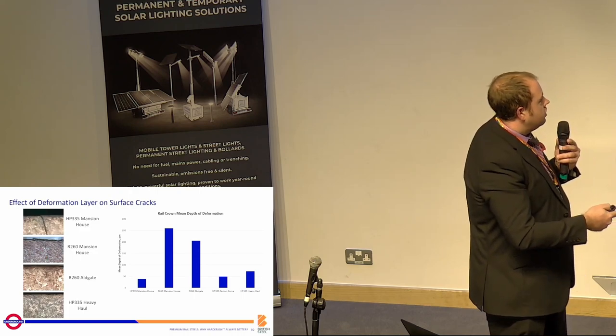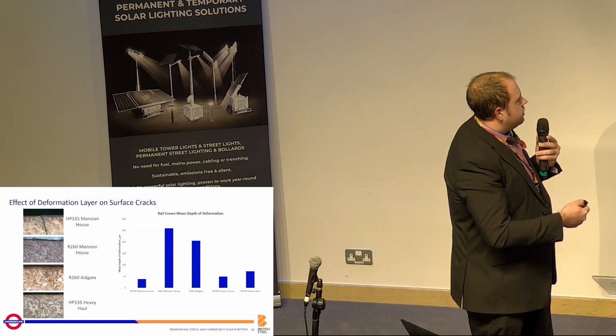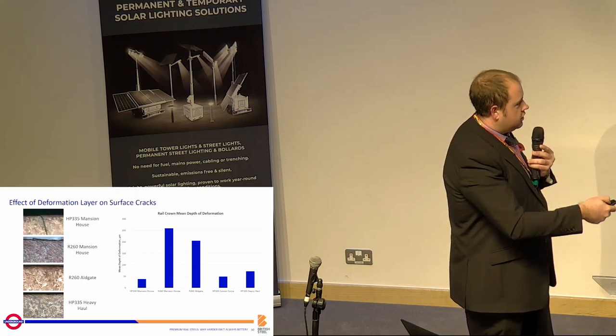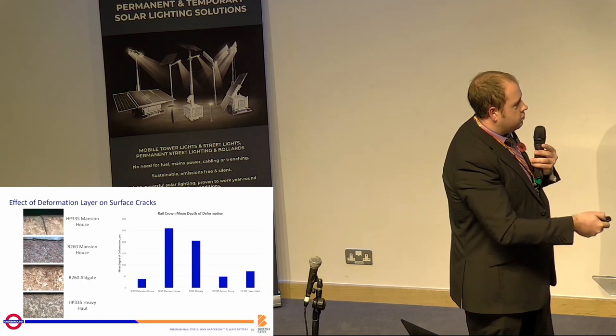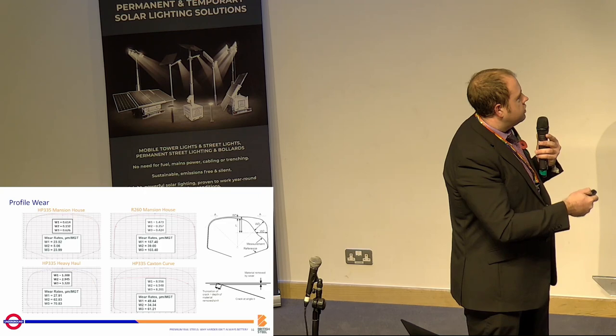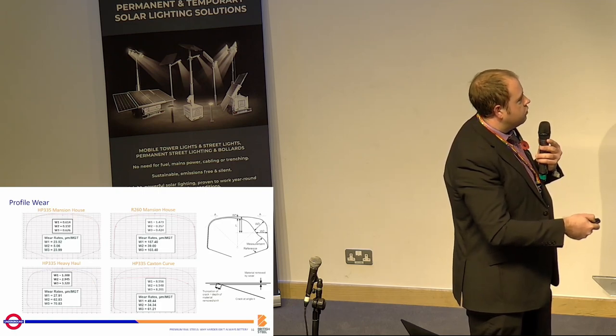This concludes the point I'm trying to make. Looking at R260-grade rail, you get a plastic deformation layer at the surface, and when a crack forms, it's constrained by the direction of plastic deformation. With harder, more premium rails, that layer is thinner, so the crack is not as constrained for as long. You can see that from this bar chart: in the R260 cases you've got a 200-micron deep layer, whereas in the premium rail cases, your deformation layer is much more shallow. This table shows the four different rails we looked at and their different wear rates — comparing the original rail Andy sent us with the rail from Caxton Curve, showing the much higher wear difference between the two scenarios.